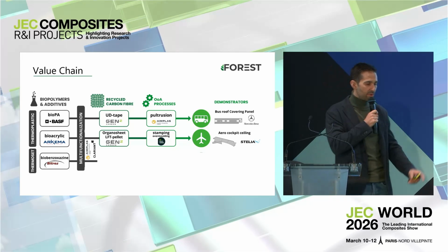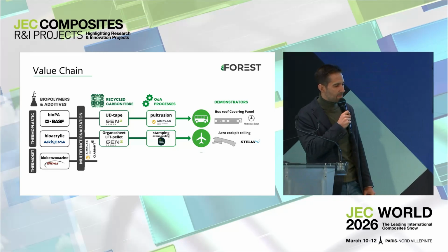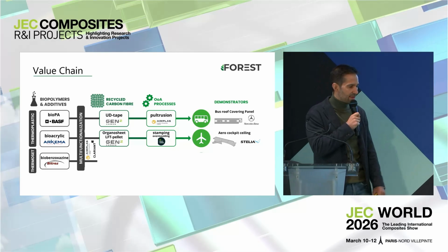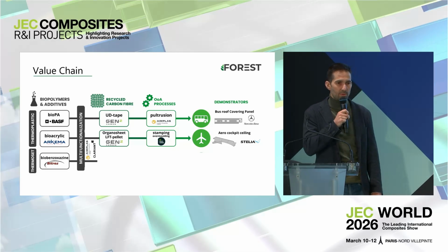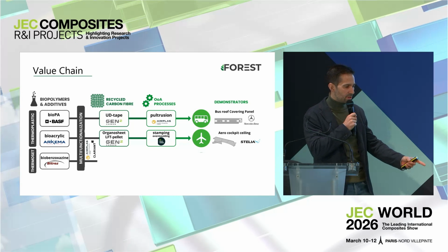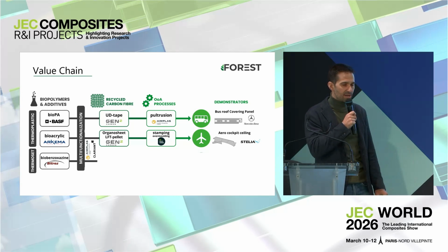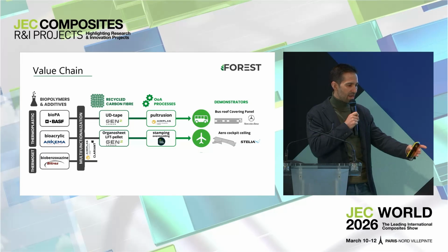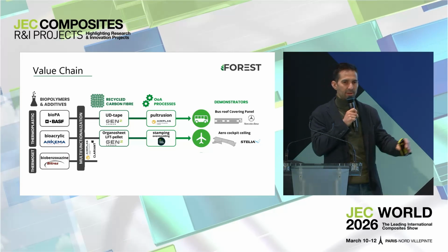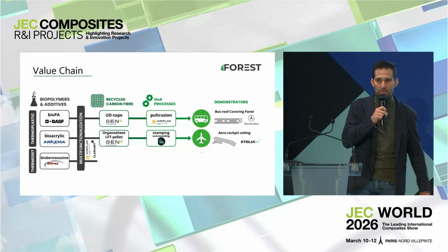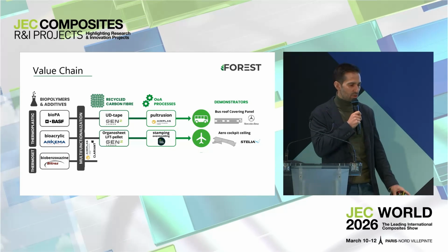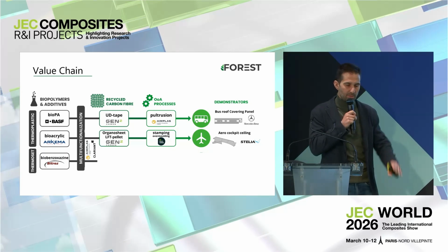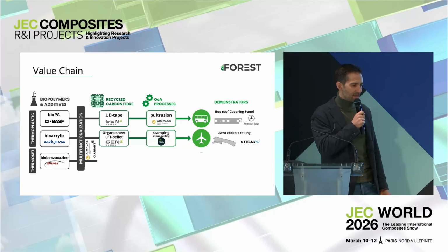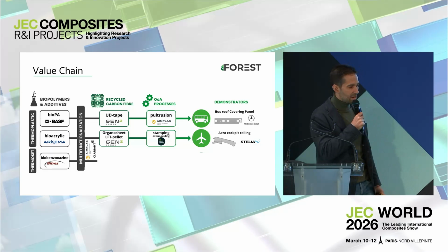The second resin, the acrylic resin, has been combined with non-woven recycled carbon fiber, also developed by Gen2Carbon, by a CRTM process in order to obtain organosheets, which were afterwards used by Jules Verne in a stamping and overmolding process to obtain the second demonstrator, which is an aerocockpit ceiling part. It's led by Stelia, which is now Airbus Atlantic.